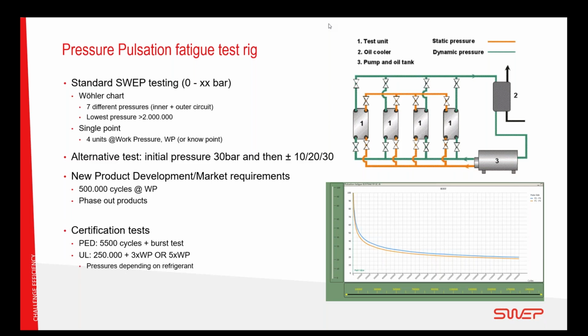Within this SWEP testing, we create a Wöhler chart, and basically we test the heat exchanger at 7 different pressures to find how many pulsations they will last before we get a leakage. The lowest pressure we test is where we reach 2 million cycles without failures. This is where we stop testing and consider the heat exchangers to last. You can also do single point testing, where we test the 4 units at a specified known working point, or at the design work pressure, for example. And then we get the chart shown on the lower right side here.